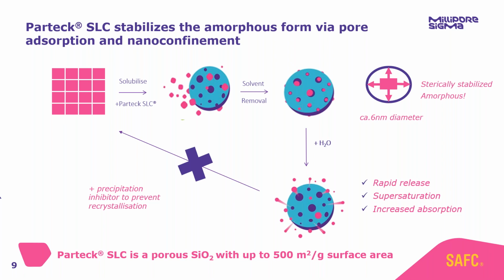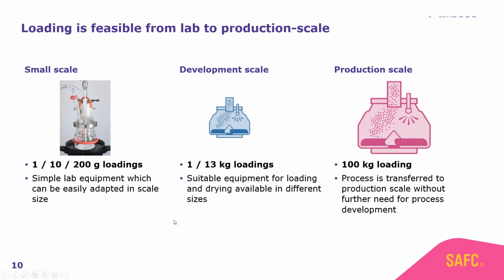So this entire model that I've just described has been reported and described as the spring and parachute model. The spring in this case is our mesoporous silica that generates that supersaturation, and the precipitation inhibitor is our parachute that prevents that rapid reprecipitation. So that, in a nutshell, is how mesoporous silica works, via adsorption to the pore and nano confinement. So let me share with you a case study on this technology, a very basic case study.